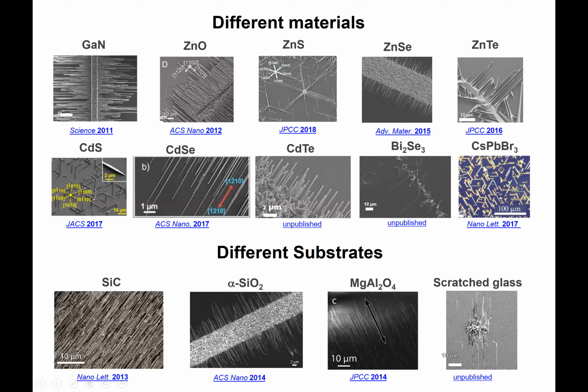There are also materials that grow by a non-VLS mechanism, like halide perovskite nanowires, which are very interesting for optoelectronic properties. We can do this on very different types of substrates, like silicon carbide, quartz, spinel, even on scratched glass.